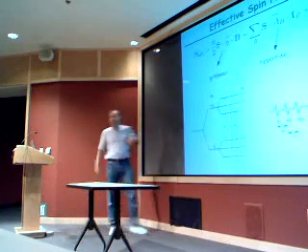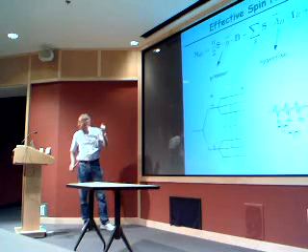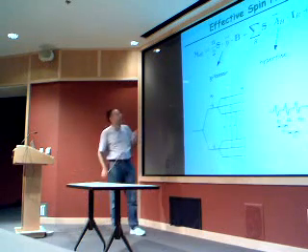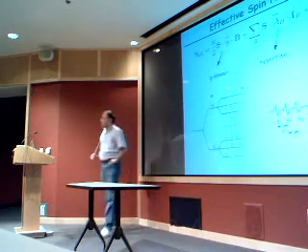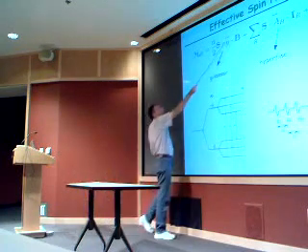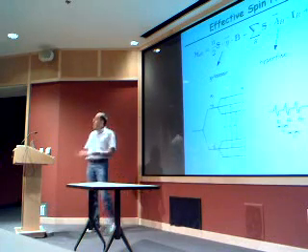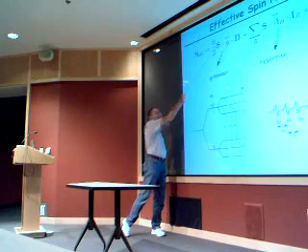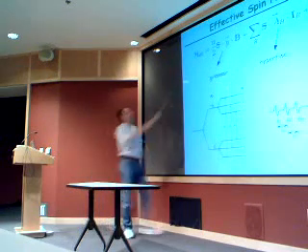So, as I said, the way it works is that the experimentalists write down an effective spin Hamiltonian. So if you couple all these terms together, mostly you get three terms. These are the most important terms. So this one, if you look at it, is nothing other than the Zeeman term, right? When you couple a spin to a magnetic field, it is S dot B. The only difference is that here you put a tensor in between, because this can depend on the direction. If you have a crystal, it depends on the direction in which you apply your magnetic field relative to the crystallographic direction, because the energy of the spin will depend also on the crystallographic direction because of spin-orbit.